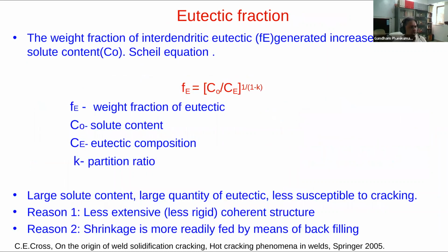And then one can go on to see microstructure effects on how to prevent cracking. The eutectic fraction of alloys is very important, because if you have some eutectic in the alloy towards solidification completion, it helps, because that eutectic solidifies at a slightly lower temperature compared to the rest of the alloy. So it is available as a liquid, and it will go and fill the gaps and therefore heal the cracks and prevent crack formation. So one solution for any alloy which has a cracking problem is to try to move the alloy composition closer to the eutectic. Eutectic means that it is easily solidifiable or castable, and therefore eutectic compositions are the best when it comes to avoiding cracks. Of course, you cannot always choose eutectic alloys, so at least you can have a eutectic liquid present in the alloy, which will help in reducing the crack susceptibility.